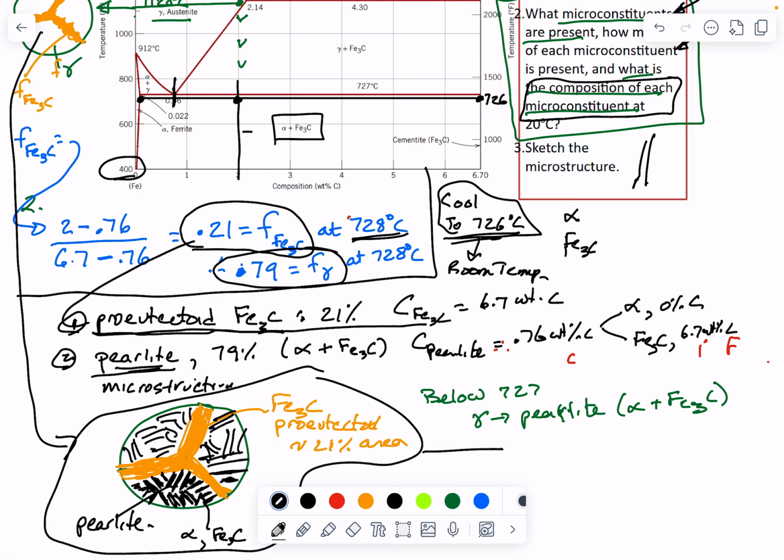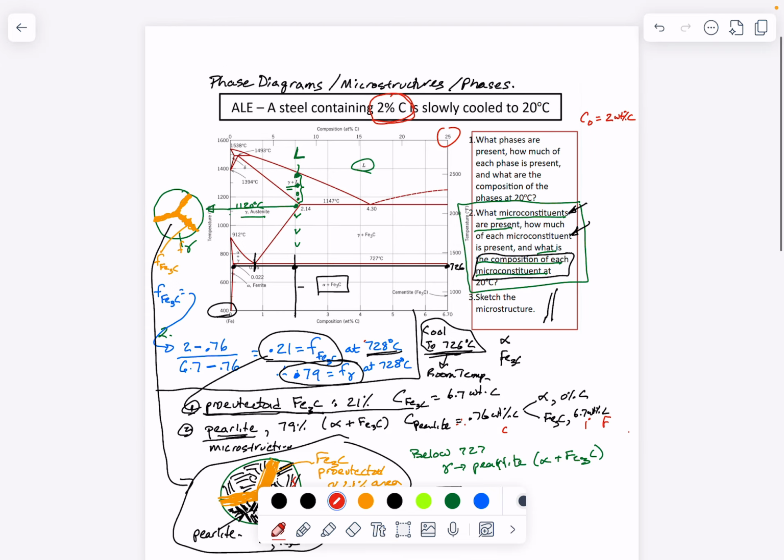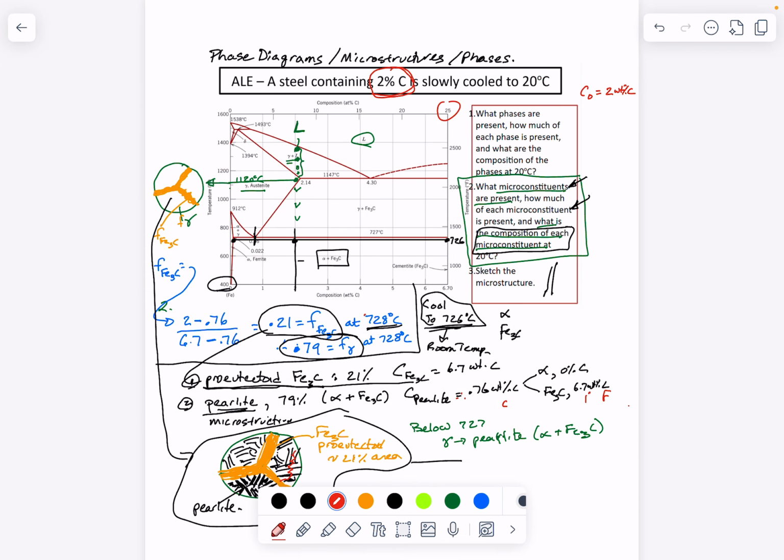Remember, a dislocation that's trying to move through the pearlite has a very difficult time moving through the pearlite, right? It slows it down immensely for a dislocation to try to work its way through pearlite. And cementite is a pretty brittle material, but it's also hard. So the properties of this particular microstructure would be that it would be a brittle but pretty darn hard material to steel. And so that concludes this extensive discussion of this particular learning exercise, and I thank you for your attention.